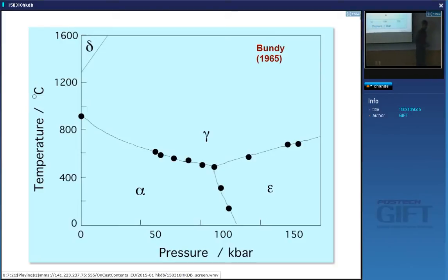But the reason why this has a larger thermal expansion coefficient is because there are actually two forms of austenite, one with a low density and one with a high density. Okay. So if I draw the two forms of austenite, and the slope here is the same as the slope here and the slope here, okay? So this is gamma 1 and gamma 2. One of them has a high density and the other one has a low density.